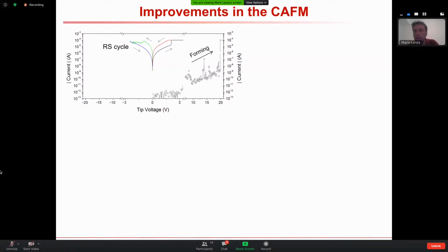Otherwise, the dielectric breakdown phenomenon is a thermal phenomenon that is self-accelerated. So if you don't apply a current limitation, you're going to make a permanent breakdown. So if you want to make a filament that is switchable, you need to apply a current limitation to limit its size. So basically, the size of the conductive filament is related to the current limitation that you apply, not so much to the material.